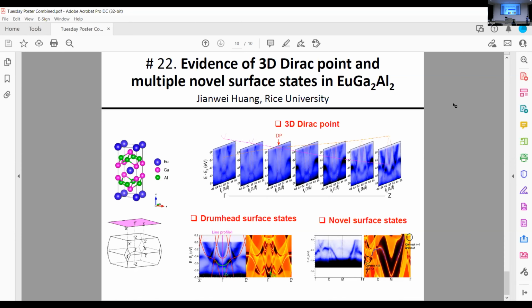We also find a novel surface state that smoothly evolves around the Brillouin zone. What is interesting about this surface state is that part of it along the gamma-X direction connects the n-2 and n-1 bulk bands, and part of it along the gamma-M direction connects the n+1 and n+2 bulk bands. These surface states should be topologically non-trivial, as they always connect the n and n+1 bulk bands. This material also has charge density wave and magnetic order, so this will be a good system to study the interplay between these orders and the topology.